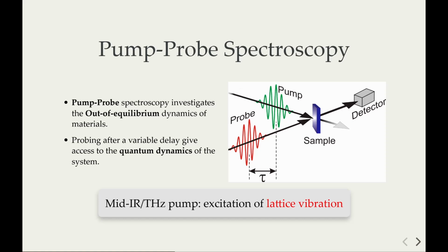We are talking about experiments that work in the pump-probe setup. Usually this means that we have a pump, a very strong, usually laser pulse that interacts with the material, brings the material out of equilibrium, and then we sample the same material after a variable time delay with a probe pulse that measures how some property has changed with respect to the equilibrium one, like how reflectivity or absorbance has changed. And since we want to study lattice vibration, we consider the pump in resonance with lattice fluctuation, in the mid-infrared or terahertz region, so it does not interact with electrons, but directly excites the lattice vibration.